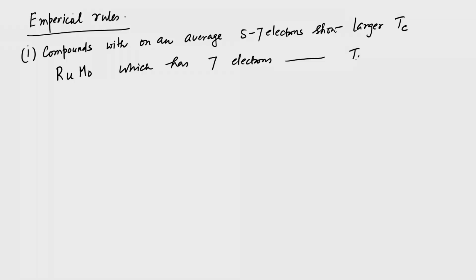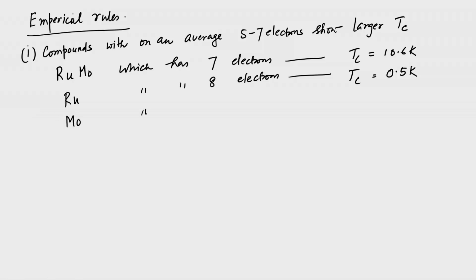This shows a TC of 10.6 Kelvin, whereas ruthenium, which has 8 electrons, shows a TC of 0.5 Kelvin, while molybdenum, which has 6 electrons, shows a TC of 1 Kelvin. So, when a compound is made of ruthenium and molybdenum, which has on an average 7 electrons, it shows a TC which is about an order of magnitude higher. Okay. And then people wanted to understand the structural dependence.